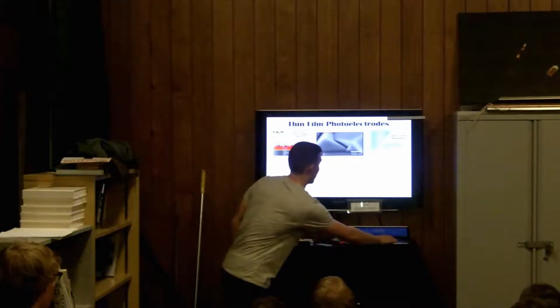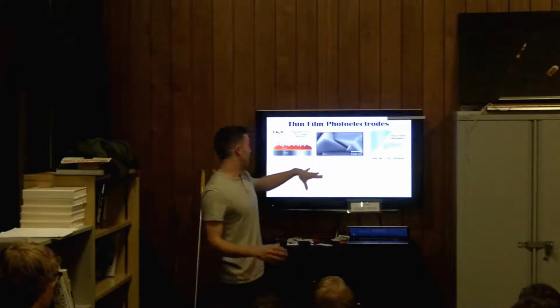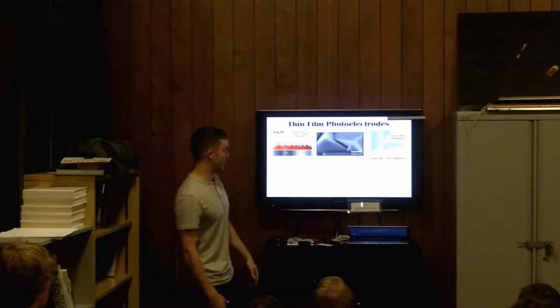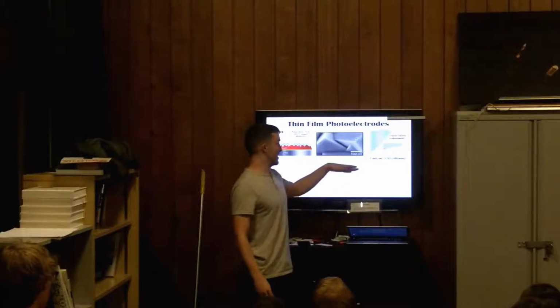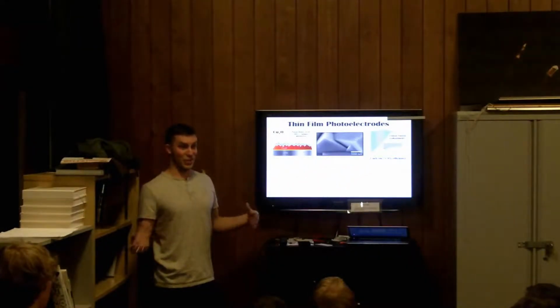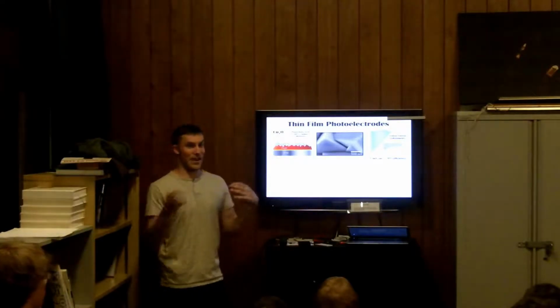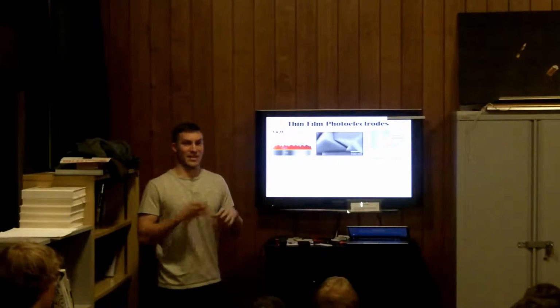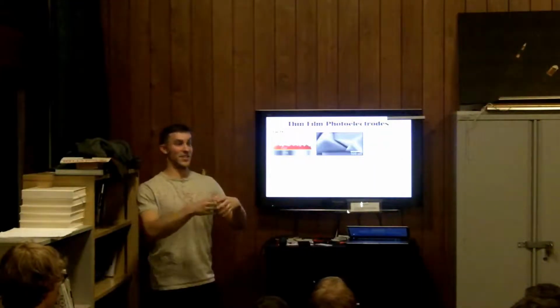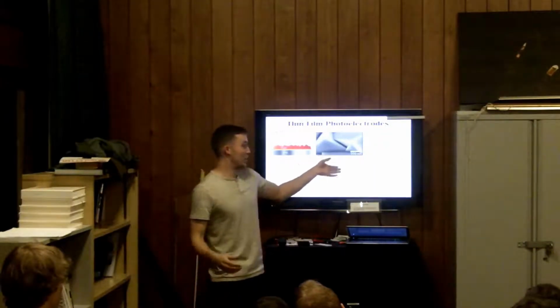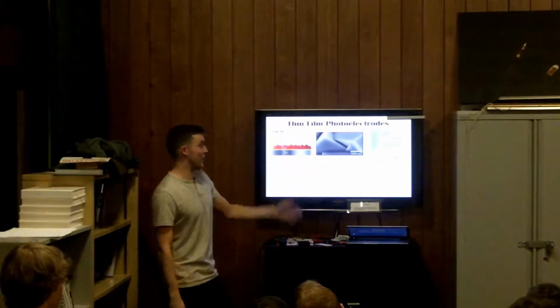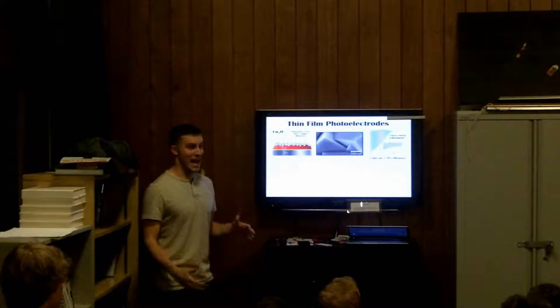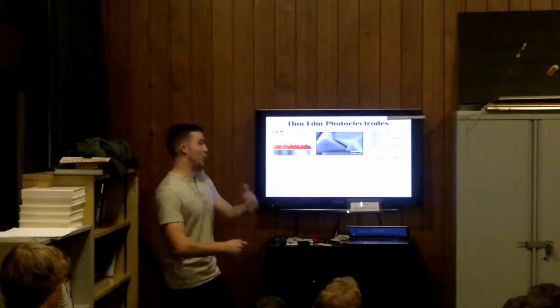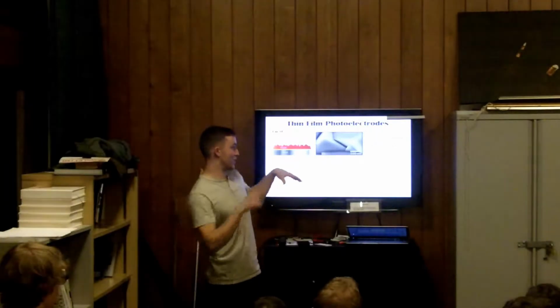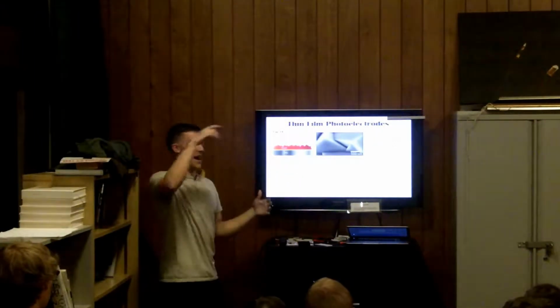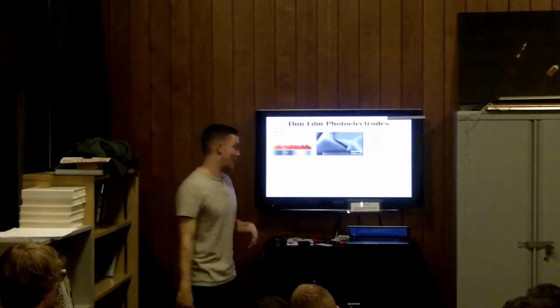And a key thing I wanted to show you here is that this material, which was not ours, was just published by another group, is achieving about 7 milliamps per centimeter squared. We present our data in terms of area because we think that the amount of energy you get from the sun is based on the area that you cover. So we present all of our results in terms of area. So 7 milliamps per centimeter squared is about a 9% efficiency. If you were able to convert all of those electrons, those 7 milliamps of current passing through, into hydrogen fuel, it would be about a 9% efficiency.